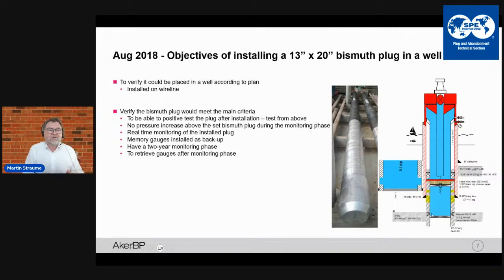So what we did was that we perforated the zone where we knew we had gas, to allow gas coming into this blue brine area below the plug. We installed a bridge plug with gauges underneath, and this bridge plug had actually holes in it, so it should allow the gas to get through, but we needed something to hold gauges - that's why the bridge plug is there. And then we had sand on top of that again, sand enough to